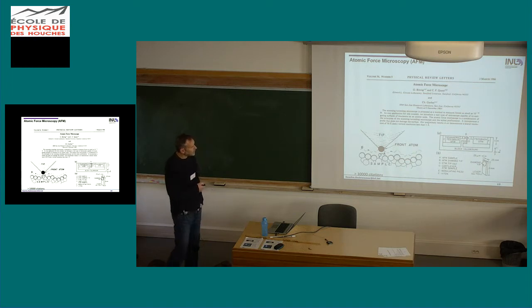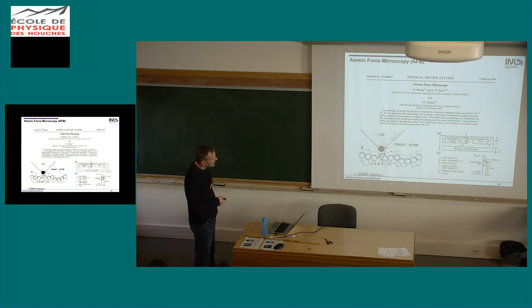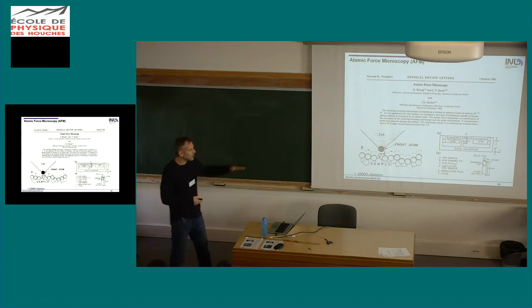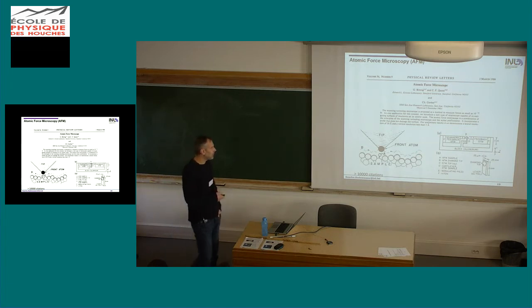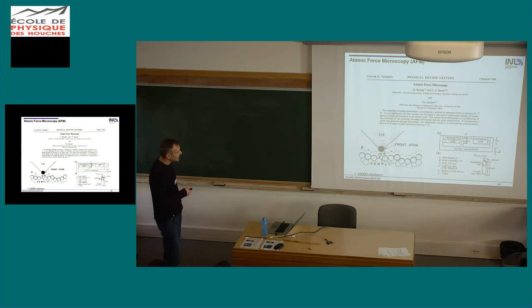They wanted to also measure insulating surfaces, and what they did was build a system that has a cantilever with a sharp tip, and on the back side of this, I think it was an aluminum foil. Yes, it was a gold foil here with a diamond tip. And then on the back side of this lever, they put an STM. So essentially, they transferred whatever was mechanically scanned to an STM. Very complicated in some sense, and nowadays it's much easier. And they were already foreseeing that you can measure interatomic forces with this.